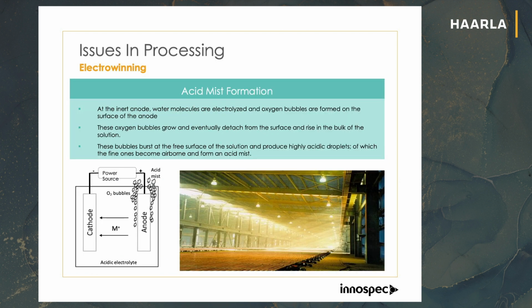The second part is electrowinning, where you get this acid mist formation. The acid mist is where small bubbles come off the electrodes and burst when they hit the surface. When they burst, they take the sulfuric acid into the air, and that causes both worker problems and corrosion of the equipment in the plant. So what we want to look at now is what influences these, and by looking at that, we can look at how we can improve the process.